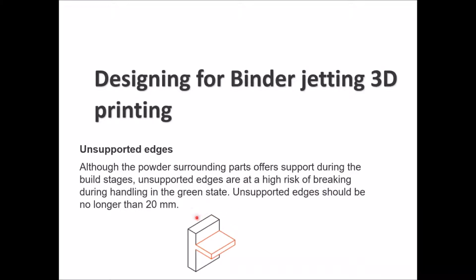For the unsupported edges, again, kind of side fins, we know that, as we discussed before, the powder is all around the part, so it's supporting the part, but unsupported edges are still at risk of breaking during handling in the green state, while they're still not fully solidified. You're handling the part, it could be pulled with something or kicked with something, it could be distorted. So unsupported edges should be no longer than 20 millimeters in length. So 20 millimeters of extruded length up from the original surface.